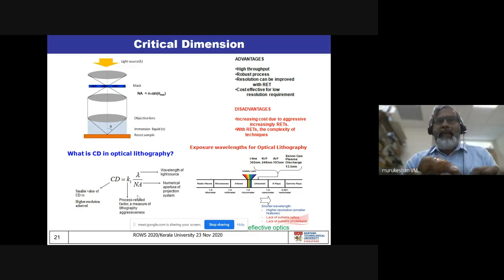And what it tells us is that if we want to reduce this critical dimension, which is our target, of course, we have to either reduce the wavelength of the light source, or increase the numerical aperture, which all of us know is the refractive index multiplied by the sine of the angle subtended, as shown in the figure. Now, if you want to reduce this, we have to reduce the wavelength. But the problem we are going to face is that most of these dimensions shown in the ITRS roadmap are already using 193 nanometer, which is already very short, or extreme UV we are reaching. But if you further reduce it, you cannot use refractive optics any more. You have to use new materials. There is a lot of research going on there.